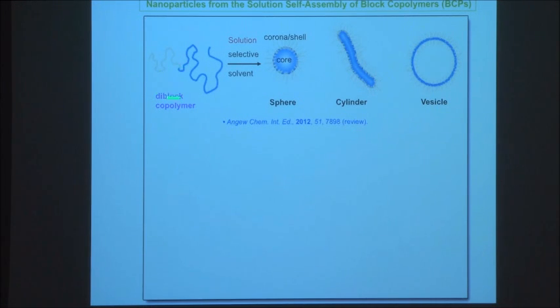And it's well known that these materials will self-assemble if you put them in a solvent that's good for one of the blocks but poor for the other, into core shell nanostructures or micelles. And most commonly, the morphology you get is a spherical structure. So if you take this block copolymer here, put it in a solvent that is poor for the blue block but good for the orange block, then you get a core of the blue block and a shell of the orange block. And these are colloidally stable structures in solution.